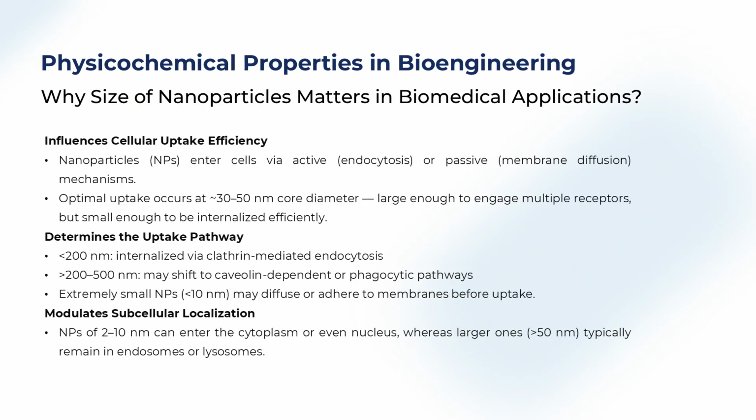If we are deciding what size of nanoparticle we should choose, we need to remember that the size will define the uptake efficiency. The optimal uptake efficiency occurs at approximately 30-50 nanometers core diameter. It is large enough to engage multiple receptors, but small enough to be internalized efficiently.